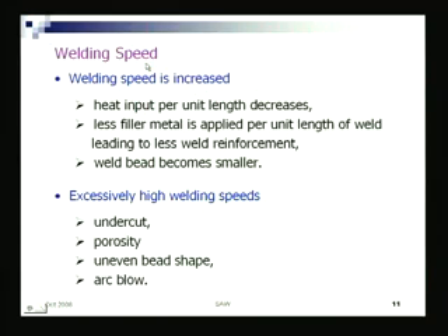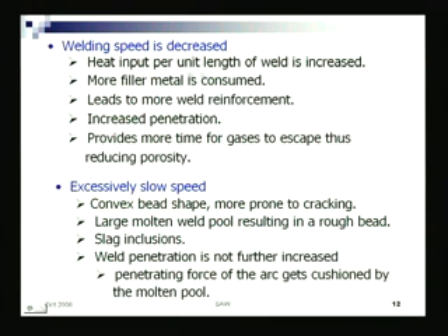Now the reverse, if we decrease the speed, heat input per unit length is increased. That is the first and foremost effect. More filler metal is consumed, leading to more weld reinforcement, and increased penetration, but not much. It is not a direct effect because the same cushioning effect of the molten metal will work.